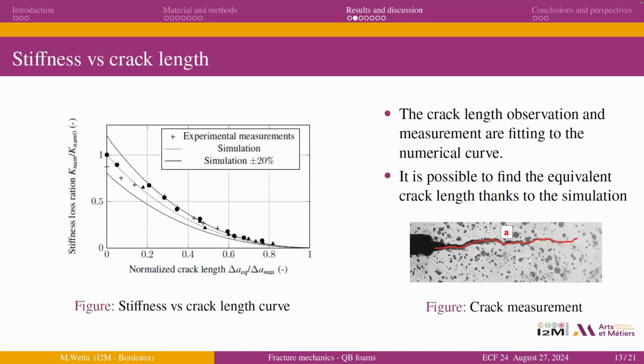So some results are presented here. The first one concerns the crack length and the stiffness as a function of the crack length. We have compared the two different options, the two different calculations. We have observed that the measurements are fitting very well. That means that the numerical estimate is good, so we can find the equivalent crack length with the numerical simulation. So that's easier to do, and it's good to have this kind of result.